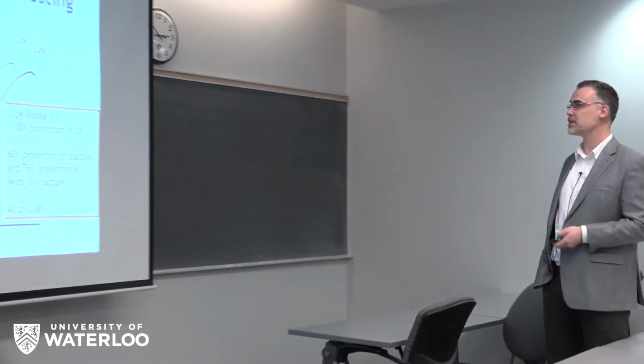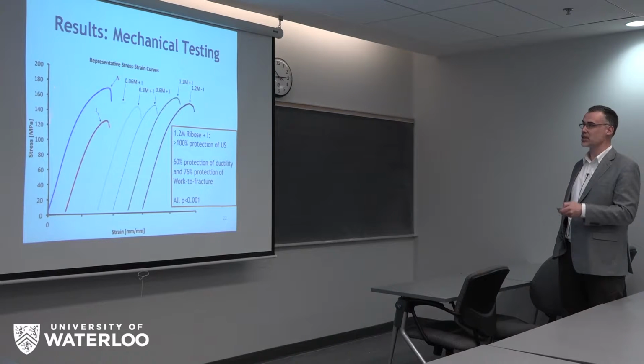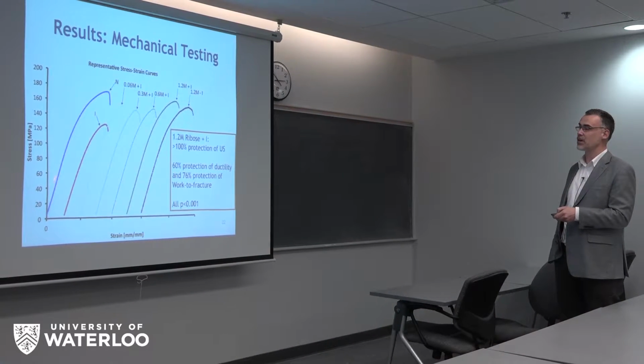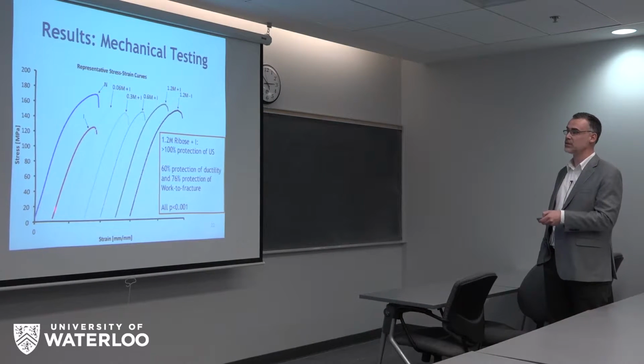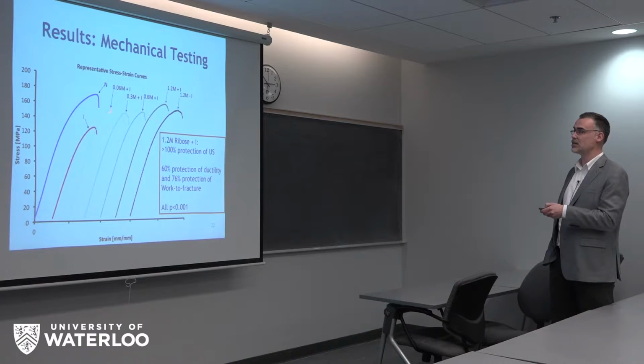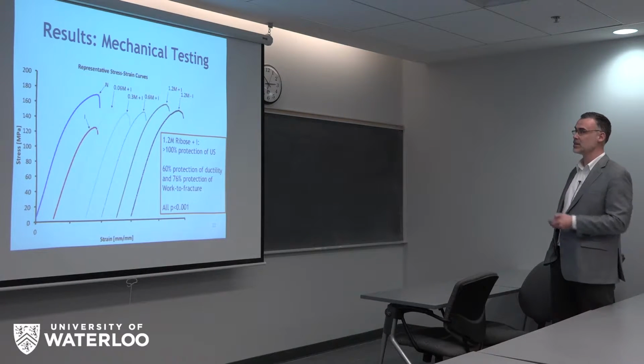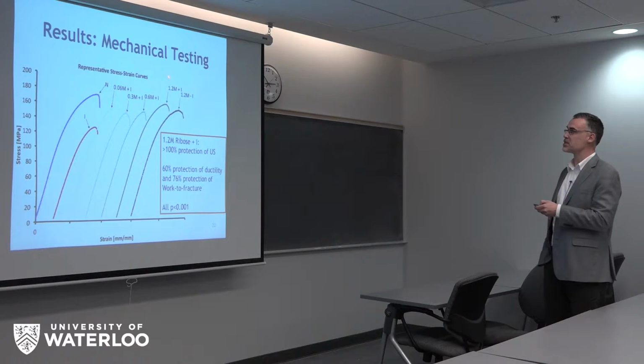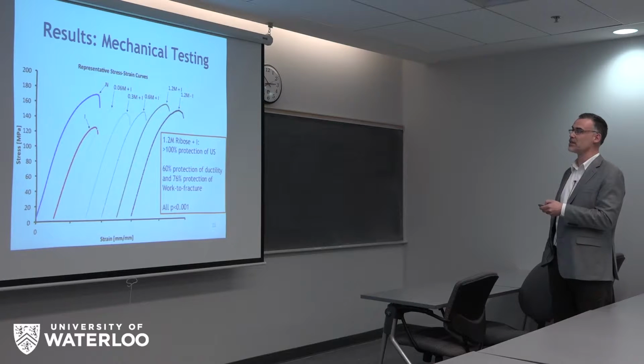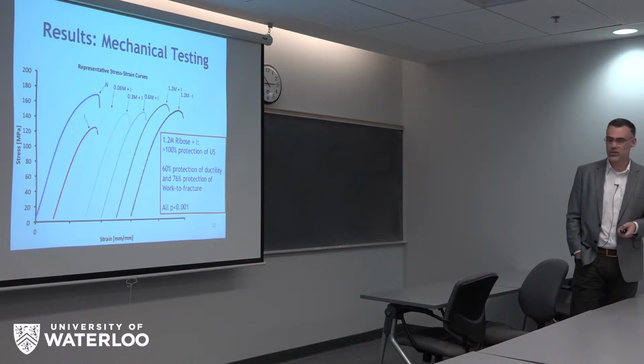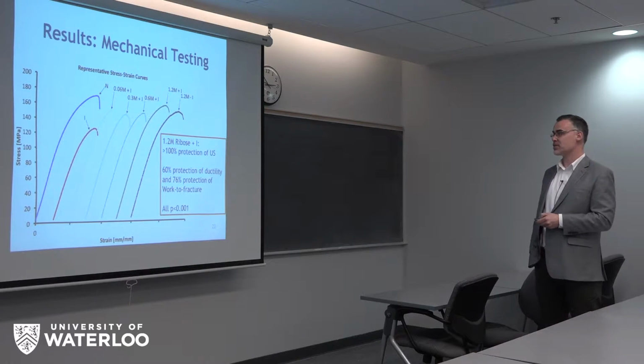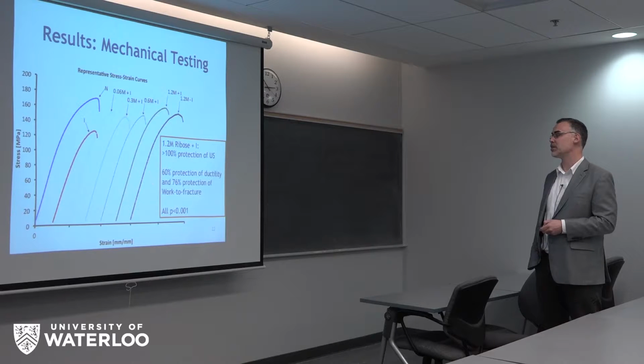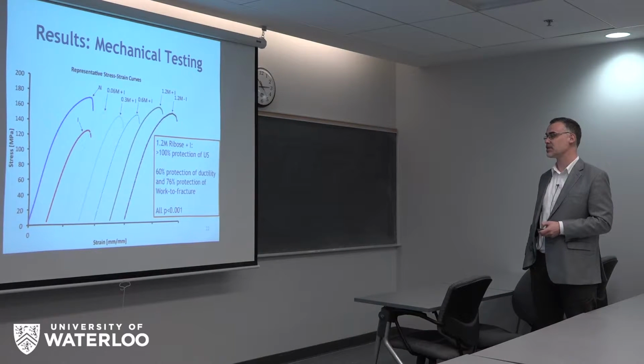So we tried a number of different ribose concentrations in this experiment, from 0.06 all the way up to 1.2 molar. The ribose solution is getting pretty syrupy at this concentration. And so you see here, these are stress strain curves from the 3-point bending. We have our control in blue, our irradiated control. You see the loss in strength and toughness, and then a gradual increase in protection, especially at 1.2 molar. And for comparison, there's 1.2 molar without the irradiation, just to show that by itself, the ribose protection treatment doesn't seem to do very much. So really promising results: 100% protection of strength, like we saw in the bovine bone, and protection of work to fracture. So that was very exciting.